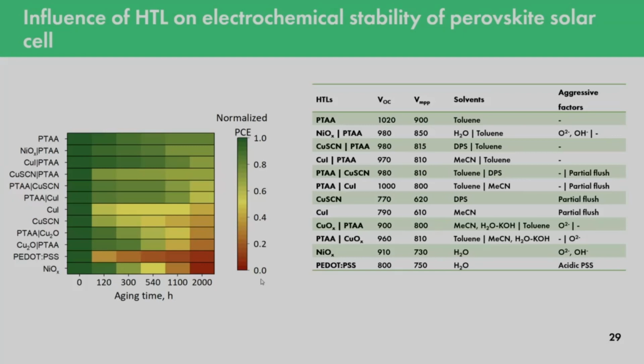It's just an assumption. And you can see that the top of the rating belongs to the hole transport layers where PTAA, polymeric, is fully chemically inert towards perovskite material, with toluene, which is also completely inert towards perovskite solvent, and those materials are not flushed by perovskite solvents also. And if you look at the top of the rating, you can see that the higher the open circuit voltage of the device, the higher the stability, and also the higher the maximum power point for the device, the higher the stability.